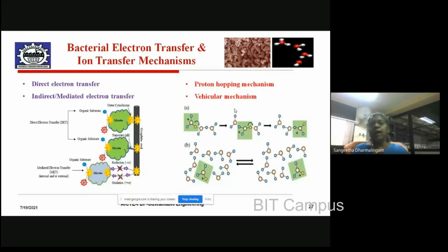Therefore, a good electrolyte membrane is one where the proton hopping mechanism is supported because of the presence of the sulfonic acid groups or any other suitable groups that may allow the protons to get transferred. Number two, it should be slightly hydrophilic, and it should not be too hydrophilic. If it is too hydrophilic and swells too much, the dimensional stability will go off, and that will give you bonding trouble, the bonding will loosen and other problems will be created. Therefore, the hydrophilic nature should be maintained at an adequate level, and this water presence is going to make the vehicular transport also take place.